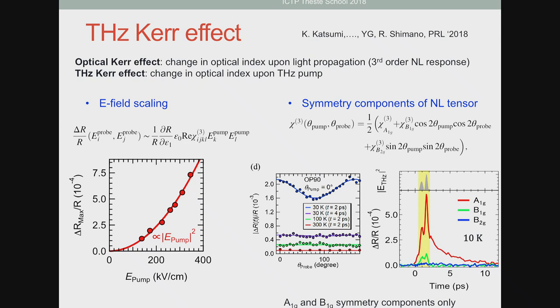And what you see here is the angular dependence of the signal by fixing the pump and varying only the probe. And what you can see is that there is a constant term, and there is a term that is also oscillating, and is oscillating as cosine 2 theta. Now, you can actually extract all the components, and what you see is that the terahertz Kerr signal is dominantly A1G. So this is this isotropic component. And there is a subdominant component here in green that goes as cosine 2 theta. So there is a subdominant B1G component.